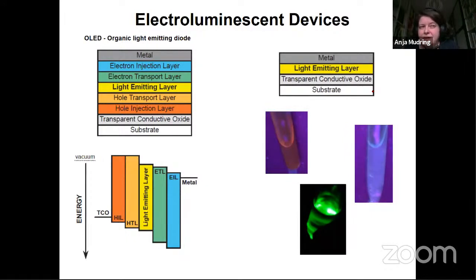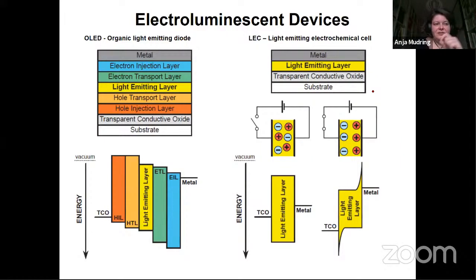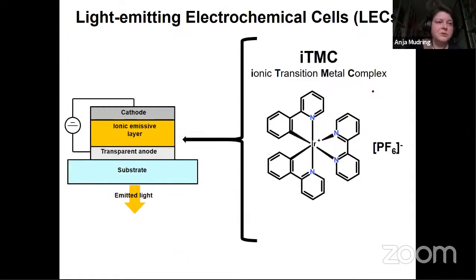And the light emitting layer, that's where ionic liquids, again, just to close the cycle, come into play. Because in order to avoid this multi-stack architecture that you see on the left side of the slide, you now just take something that contains cations and anions, and when you apply a bias, they migrate in the applied field, create electric double layers on the respective electrodes, and you generate the potential drop that otherwise gets created through the individual layers just by the ion distribution. It's very simple.